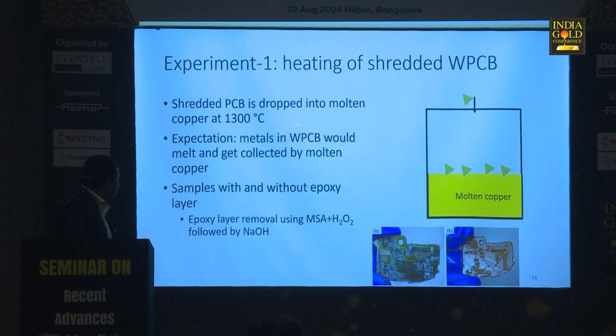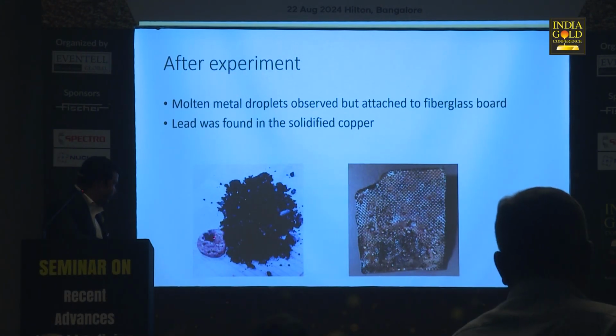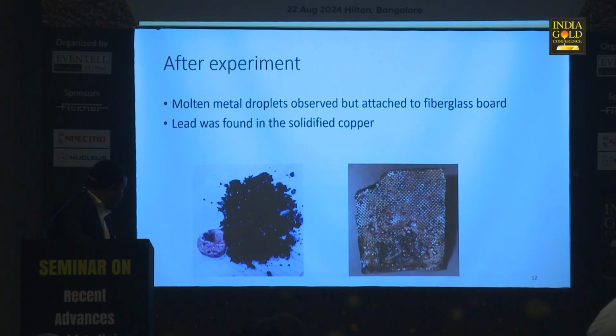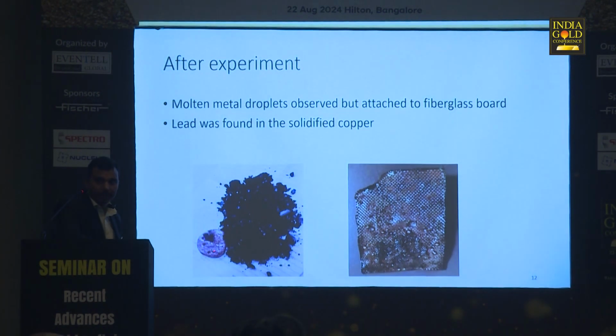So we had shredded PCB that was dropped in molten copper at 1300 Celsius. And the expectation was that metals in the PCB will melt and get collected by the molten copper. We tried both with epoxy and without epoxy; both types of experiments were done. However, after the experiment, we found this. So there is some discoloration of the copper. Primarily, we found there is some lead that has gone into the copper, but there is a lot of unmelted residue, which looks like this.